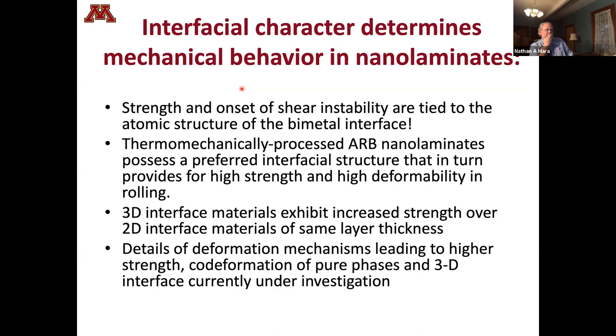So what we've seen overall in the copper niobium system is that the strength and the onset of shear instability are really tied to the atomic structure of the bimetal interface, right? Our mantra, it's all about the interface, still holds here. We've got ARB nanolaminates that get this nice preferred interfacial structure throughout them. And we find that 3D interface materials end up enhancing the strength over 2D interfaces of the same layer thickness. So you can actually enhance the properties without changing the morphology or the chemistry very much.